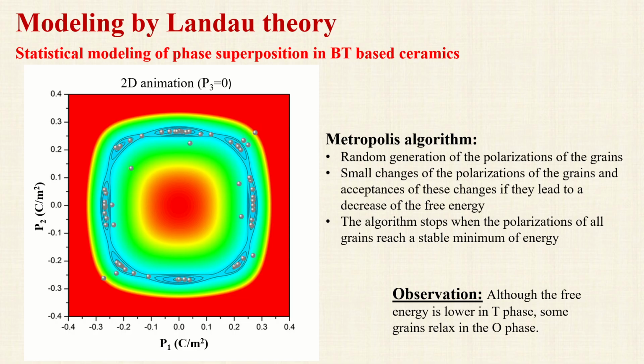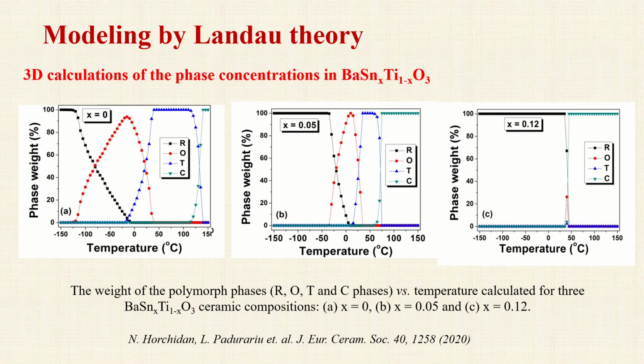As expected, many grains relax in the tetragonal phase, which is characterized by the lowest energy in this example. However, other grains relax in the orthorhombic phase, which is also a stable minimum of energy. Using this procedure for 10,000 grains, we are able to estimate the concentration of the phases in the equilibrium state.